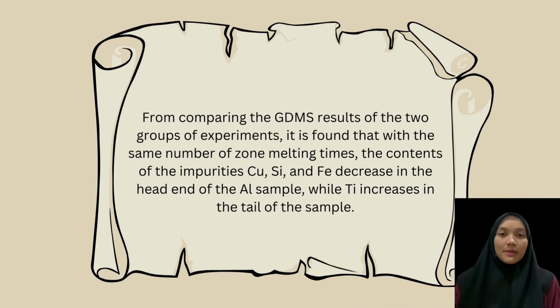From comparing the GDMS results of the two groups of experiments, it is found that with the same number of zone melting times, the contents of the impurity copper, silicon and iron decrease in the head end of the aluminium sample, while titanium increases in the tail of the sample.